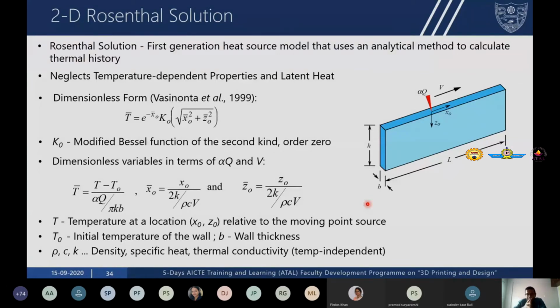It's called the Rosenthal solution. It is a first generation heat source model that is using an analytical method to calculate the thermal history. Now you can see here a thin wall geometry, okay, and the dimensions of this thin wall, the length, width, and height, are such that the geometry can be considered as semi-infinite. The Rosenthal solution makes several assumptions. The first assumption is that the properties of the material are constant. They do not vary with temperature, but in actual physical sense, the properties of the material vary with temperature. The geometry is infinite or semi-infinite. That is, the dimensions of the geometry are such that the melt pool never sees the free edges. Then the heat source is a point heat source, and the energy of the heat source remains constant, and the speed of travel of the heat source also remains constant. Now, in 2 dimensions, the Rosenthal solution is given in dimensionless form.